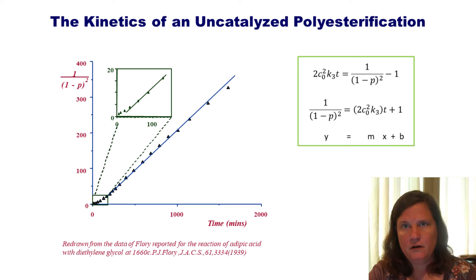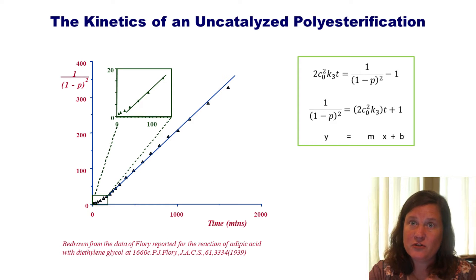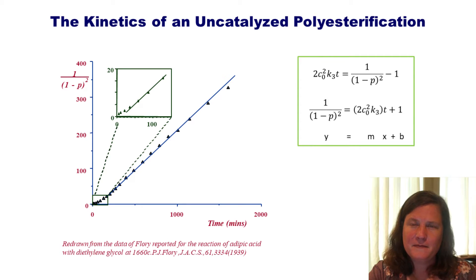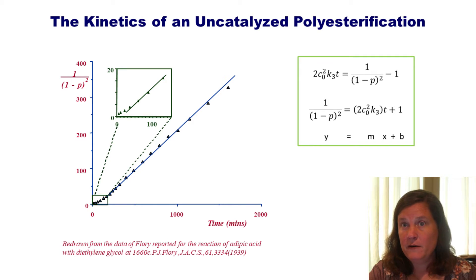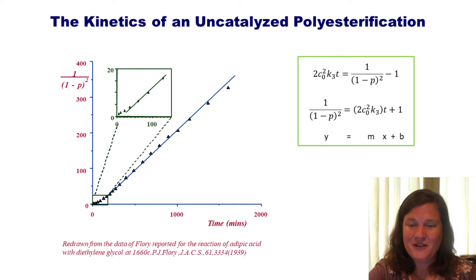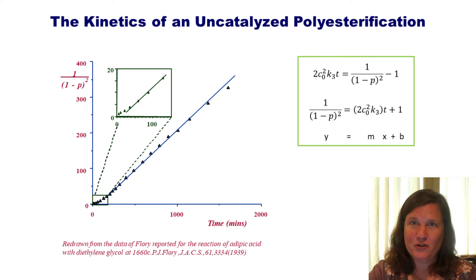The plot of 1/(1 − P)² versus time is very linear, except at really short times — and that means our assumptions are valid. Why is it not linear at very short times? The reactivity assumption holds except for monomers and dimers, which react a little bit faster. So we see a deviation toward a faster rate at very short times, consistent with the Flory data we saw earlier.